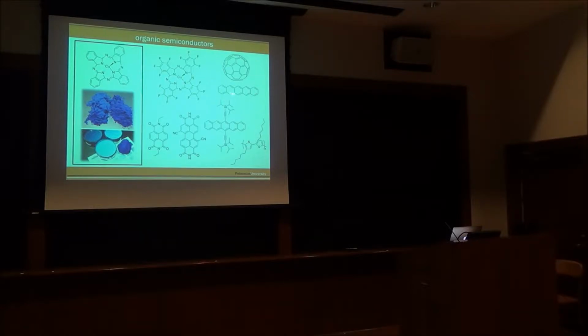This is pentacene. You can buy it, and people have used it for 3 decades now to make organic circuits. But it's not solution processable, so you'd have to thermally evaporate it to deposit thin films out of it. But by adding these greasy side groups, now this pentacene molecule, called TIPS pentacene, is solution processable. You can put it in an organic solvent, make an ink or a formulation that you can then spread over large areas. This is poly-3-hexylthiophene.